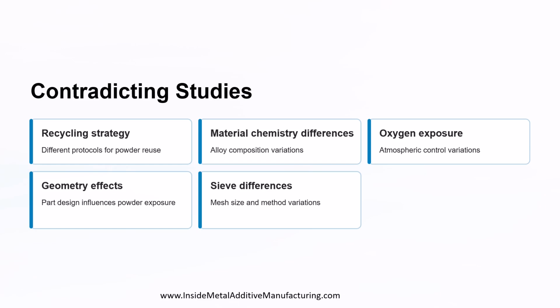Third, oxygen exposure varies from machine to machine and from one facility to another. Fourth, the effect of oxidation depends heavily on the material itself. IN718 tends to be chemically stable, while titanium alloys are extremely sensitive to oxygen pickup. Fifth, build geometry affects how much spatter is generated. Lattice structures, for example, tend to degrade powder more aggressively. And finally, even the spatial position inside the build chamber, north versus south, front versus back, can influence both powder degradation and mechanical properties. Understanding these variables is crucial for designing a recycling protocol that is predictable and repeatable.